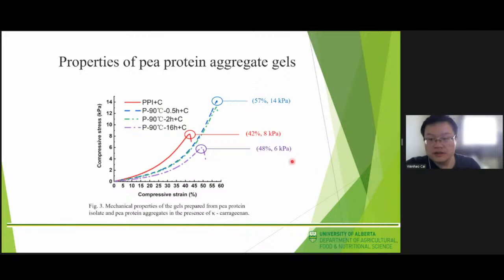Actually, no significant difference was observed for the gel mechanical property when they were prepared from 0.5 or 2 hours aggregates. However, the gel compressive strength was decreased to 6 kPa when the gel was prepared from 16 hours aggregates as the building blocks with κ-carrageenan. This result suggests that elongated pea protein strand aggregates might be less active for gel formation when compared to the shorter pea protein aggregate particles, possibly attributed to the reduced surface hydrophobicity.